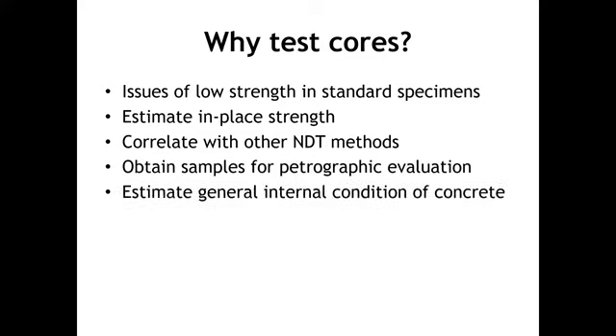Normally the core is extracted with a diamond fitted wheel, and the minimum diameter of the core should be 94 millimeter, or 2 times the maximum size of the aggregate. But in the field, 69 mm is what is being used by us and many other consulting companies. The reason behind it is the rebar. The rebar spacing normally comes to about 75 millimeter maximum. So in between, 94 millimeter will not be possible, and we want to avoid cutting of the reinforcement. So we go for 69 millimeter.